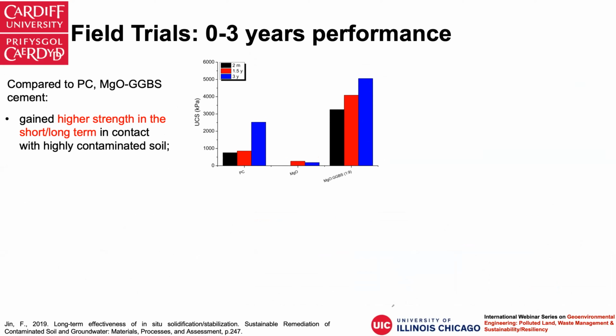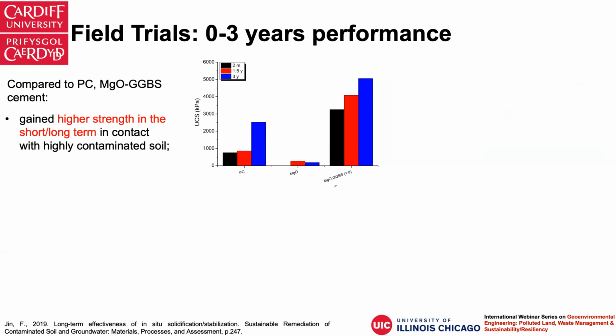So we see that in this very complex field soils, contaminated by various heavy metals and lots of PAH and total petroleum hydrocarbons as well, it's very complex, but we see that using magnesia and GGBS blends, it develops much higher strengths, both in the short term and in the long term. That demonstrates the good compatibility of this cement with these complex contaminants.